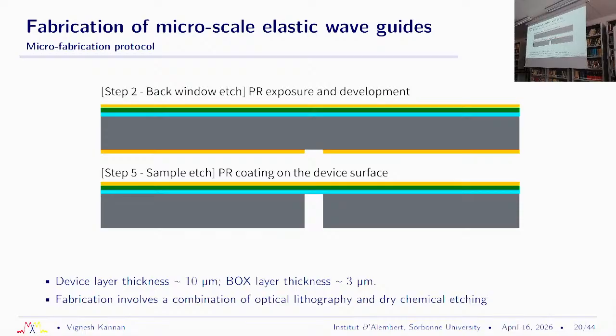Now, in our case, the limitation was about 1 micrometer, because we use UV light to essentially expose specific regions of this photosensitive polymer. The UV light has a wavelength of about 350 nanometers. Technically, that would mean that you have a resolution of 300 to 600 nanometers, but then you have issues with the optics, and you have focusing, and you have diffraction limitation, and effectively we have a practical limitation of 1 micrometer in our etching process, in our photolithography process.